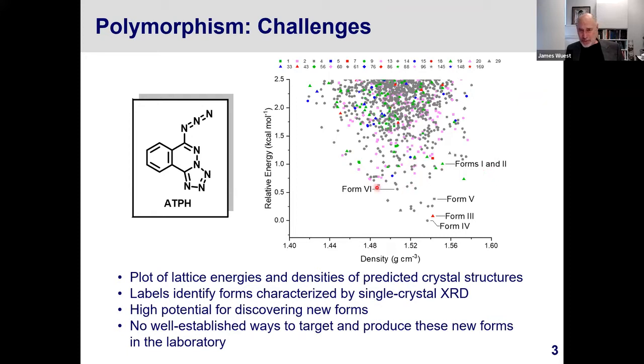So what you see here is interesting because the forms that we have been able to find for this ATPH compound are marked specifically. We have identified and characterized by single crystal X-ray diffraction 7 different polymorphs of this compound, which is an achievement we're proud of. There are a lot of different polymorphic forms, but you can see from this plot that there's a lot more work that needs to be done to uncover more polymorphic forms. It's well understood that crystal structure prediction over-predicts the number of potential forms, but even if there's a degree of over-prediction, there's still a lot of undiscovered polymorphs in this series.